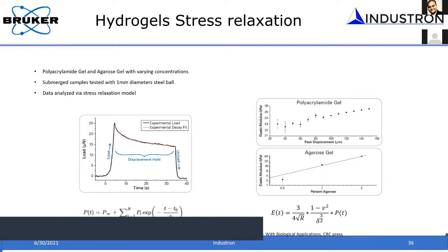You can also do load relaxation type experiments where you apply a load and keep the load constant and measure the displacement as a function of time, or apply a load and keep the displacement constant and measure the load relaxation as a function of time. And then use this load relaxation curve to fit this part of the curve and measure the relaxed elastic modulus. You can do that also.